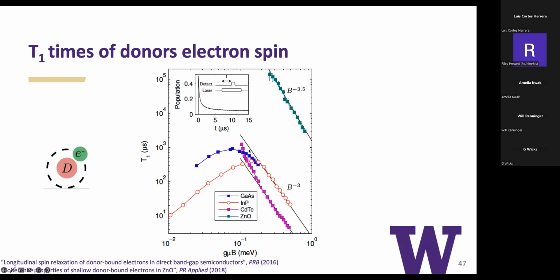And so our first test was we had done a study of gallium arsenide, indium phosphide, and cadmium telluride and really worked hard to understand what causes spin relaxation in this material. And it pointed the way to looking at zinc oxide, which involved doubling all our lasers. And I'm happy to say that that's where undergraduate researchers come in handy. If anyone's an undergraduate in the audience, undergraduates are willing to be bold and go where no one has gone before. I had a wonderful undergraduate researcher who says, I'll try that. And the first results that came out showed about a 1,000-fold increase in the spin lifetime because we had moved to this different host matrix.